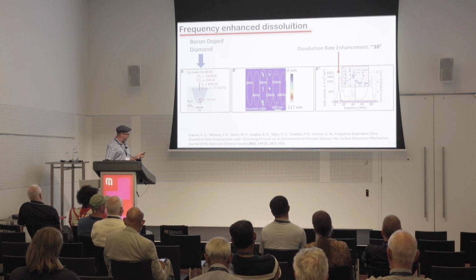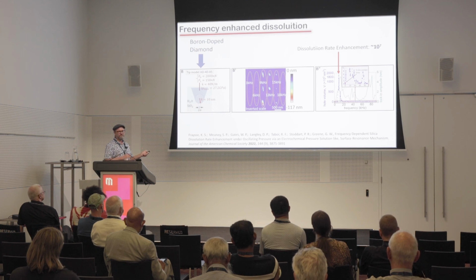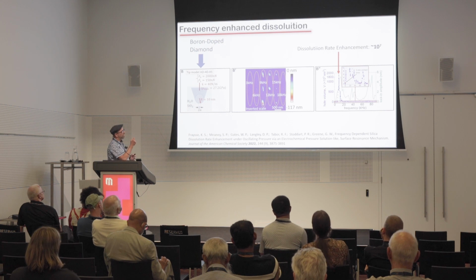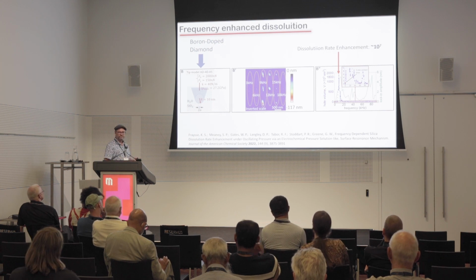And more importantly, if you look here at the peak dissolution, right? So this dissolution rate right here is a dissolution rate enhancement of the silica surface of 10^7, so 10 million times faster than silica should normally dissolve. Now, these are the kind of etching rates that you get in solutions of hydrofluoric acid, but we're observing them in essentially deionized water.